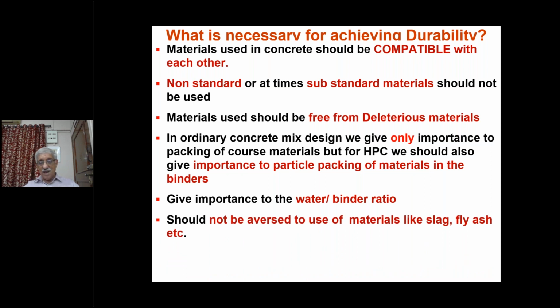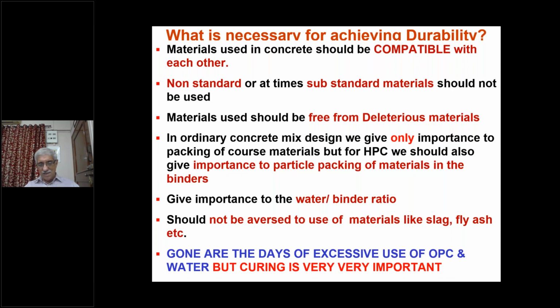One should not be averse to using materials like slag, fly ash, etc. When I was training the engineers in Ambuja Cement, I used to always say that you will never be able to make high performance concrete if you don't use materials like slag, fly ash, etc. Of course, of the correct specification. Otherwise, you will lose this waste material and not make a concrete which is durable and also sustainable, because these materials should not be wasted, in my opinion. Gone are the days of excessive use of OPC. These materials also help in reducing the cement content, though not the cementitious content, and the water also.